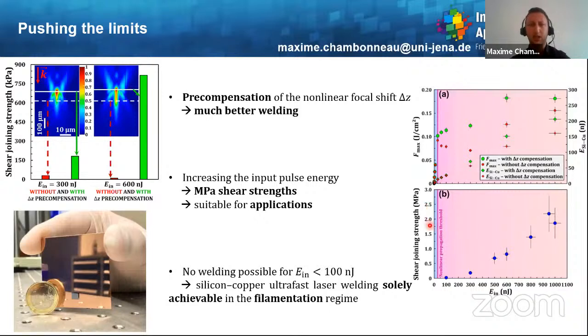Interestingly, one can note that there is no welding possible for input pulse energies below 100 nanojoules, meaning that silicon to copper ultrafast laser welding is solely achievable in the filamentation regime, which justifies completely our approach of measuring and precompensating